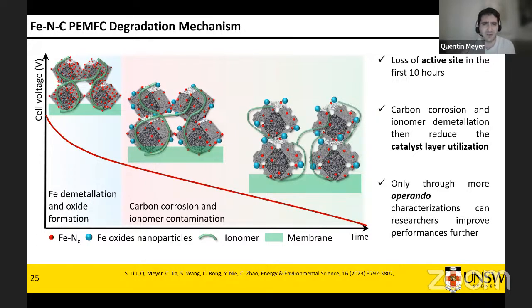By way worse, I mean the interaction with the ionomer that was initially very good becomes weaker and weaker. That's because literally you have less particle for it to attach to. At the same time, you have a lot less active sites. You may generate more heat against carbon corrosion, so your ionomer is going to shrink simply because there is more heat, so it starts to dehydrate. And this is going to give you a lot of problems.